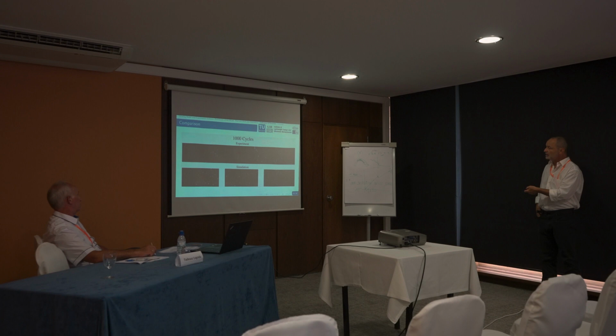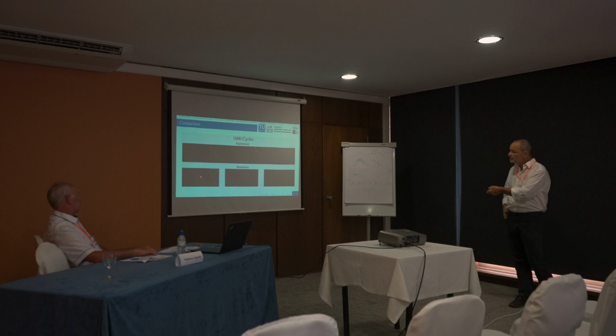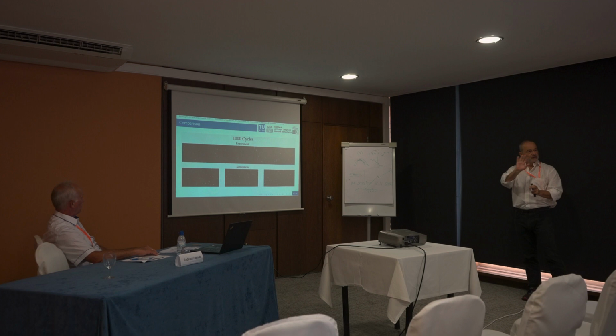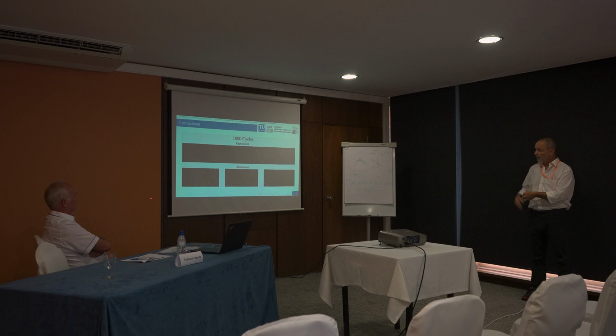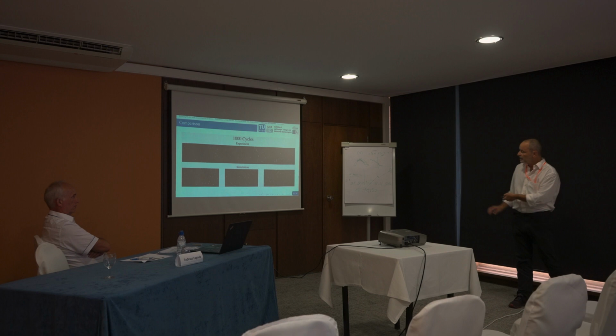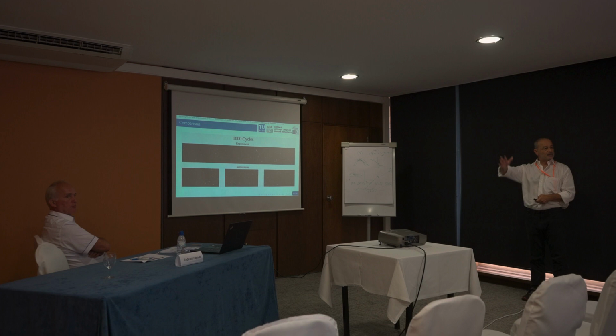That's the experiment. We have a cross section of the copper, and after that we have introduced these damage onset points, and after thousands of cycles, you see a certain pattern of voids growing. No crack has formed, maybe a small one here, but it starts to evolve. And our simulation looks like this. We have done it in smaller parts, but we ran different simulations with the same statistical descriptor, but a different realization to compare this. And that's the damage evolution after a thousand cycles, and if you continue, the damage grows and the crack pattern evolves.